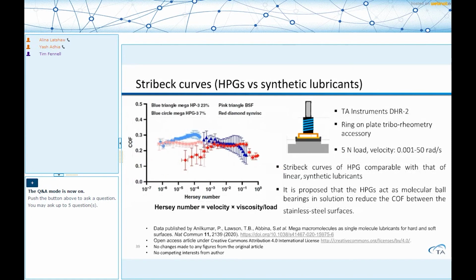And the interesting thing is when they started investigating the use of these materials in terms of its lubricity, they found that the hyperbranched polymers, which are represented in the blue circles and blue triangles, have very comparable coefficient of friction properties, of tribological properties, compared to the conventional synthetic. These molecules have a globular structure. These act as tiny ball bearings between the two surfaces that allows it to offer the lubricity that you can see in the graph over here.